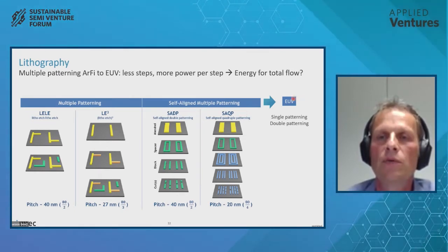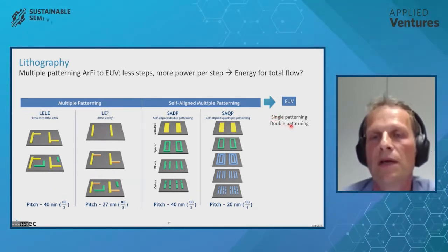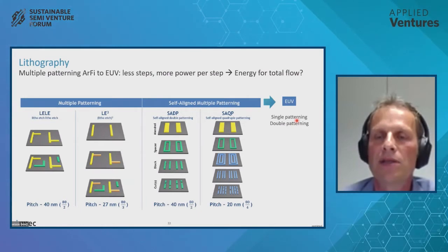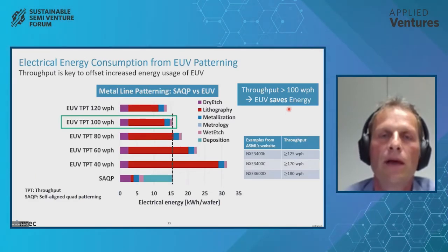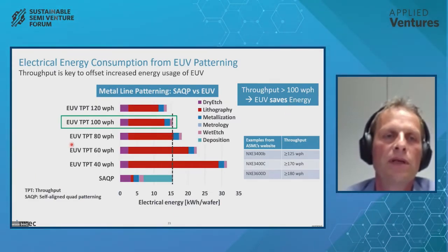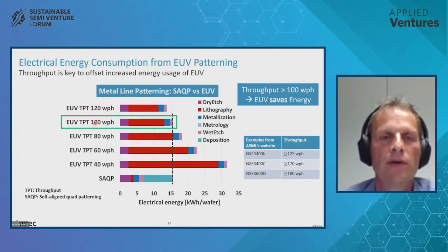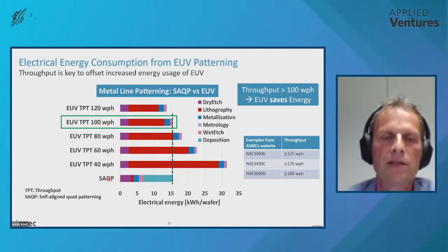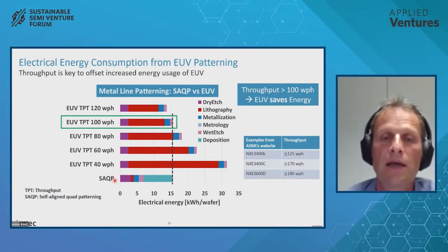Now with EUV, we can replace these by single patterning, and eventually we need to go to double patterning also with EUV. Now the question is, what happens then in terms of the carbon footprint, because EUV has this very large electrical energy need. And in fact, if the throughput is high enough, so here you see 100 wafers per hour, it's equal. So what I'm comparing here is self-aligned quadruple patterning with an electrical energy need of 15 kilowatt hour per wafer.